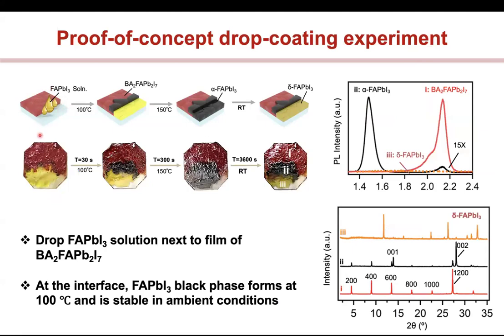And we washed away one half of this glass slide, right? We just wiped it off with a tissue and a solvent, and then we dropped this precursor of the FAPI solution. So this red is the 2D perovskite, and we dropped this precursor and let this precursor flow onto your 2D perovskite, right? And we did this at 100 degrees C.